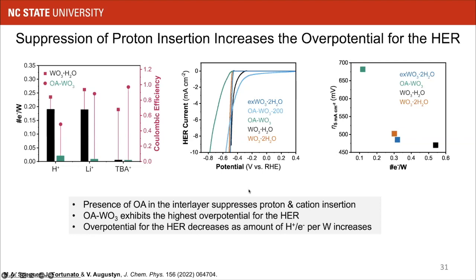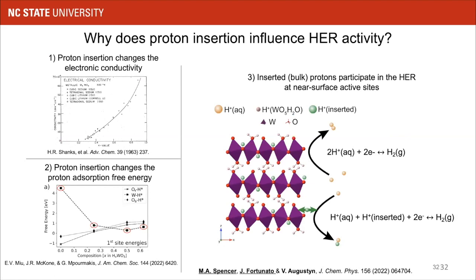Then when we look at the hydrogen evolution reaction phenomenon, we see that for the octylamine material, it has the highest overpotential for the HER. And we can further express this by taking the overpotential at a specific current of 5 milliamps per square centimeter and plotting it by the number of electrons associated with each tungsten. And we see that the highest overpotential is with that octylamine material. And then as we start to insert more and more protons into the structure, that overpotential decreases very quickly. So the open question is still exactly why proton insertion influences HER activity.